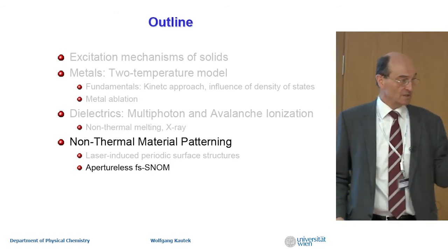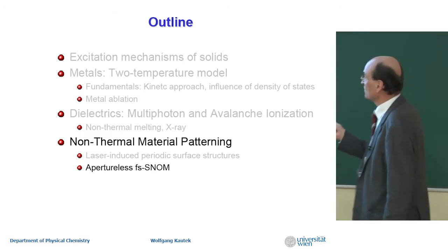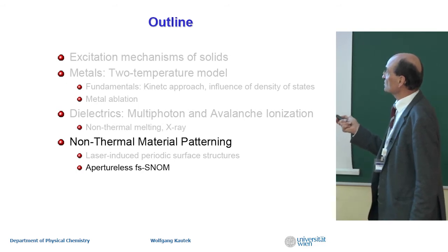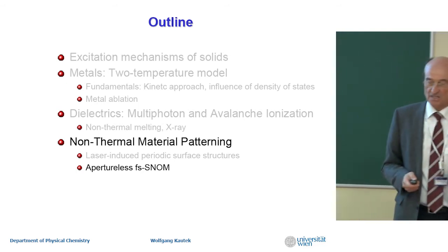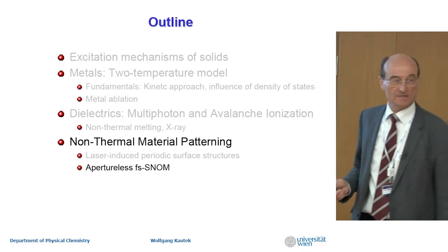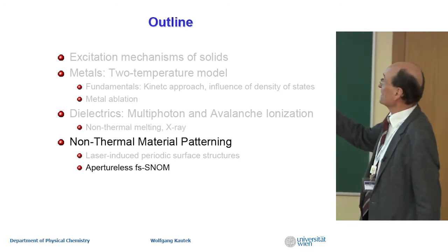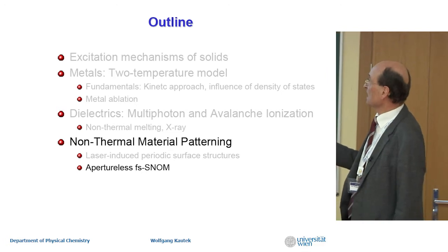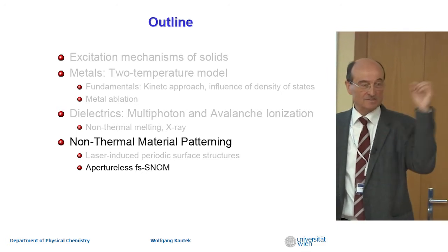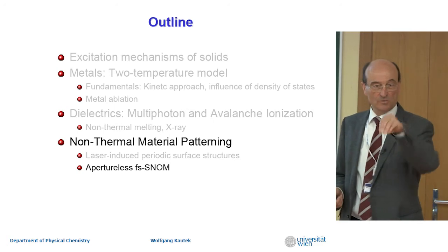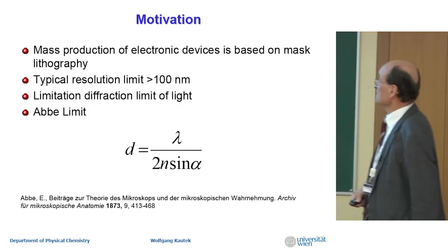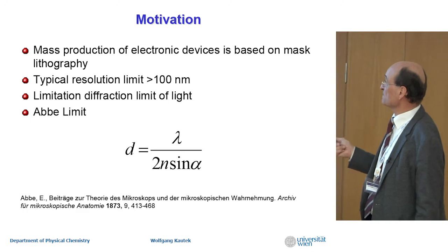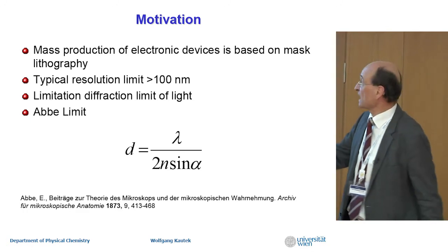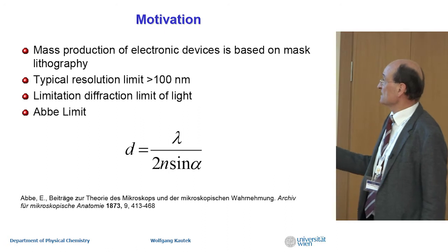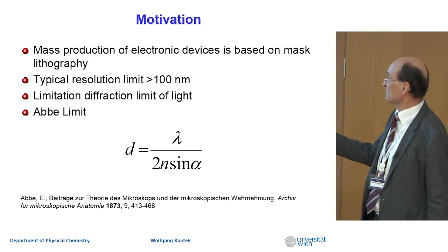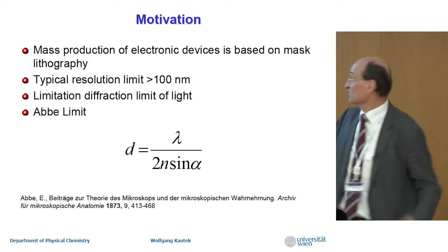At the end, let me come to a quite interesting top-down and not bottom-up structuring process, the apertureless femtosecond SNOM, scanning near-field optical microscopy. You have an atomic force microscope tip, and you excite the tip with a femtosecond laser, and you're playing with the plasmon at the tip. So the motivation is, of course, to come around the problem of Mr. Abbe. The resolution is limited by the wavelength and the aperture in the denominator.